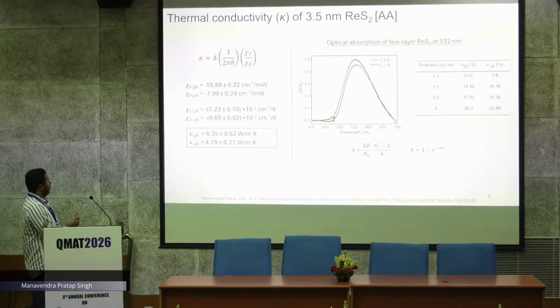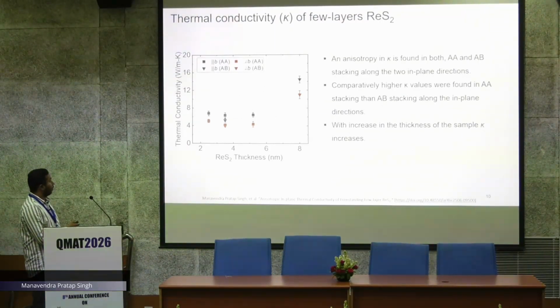So using this formula we have calculated the thermal conductivity, and we can see the thermal conductivity has different values in both directions, so there is an anisotropy in our thermal conductivity. Similarly, we have done 5 samples in different stacking and different thickness. Here we have seen 3.5 nanometer 2 samples, where the AA and AB show different in-plane direction and stacking dependent thermal conductivity, and in AA there is more thermal conductivity